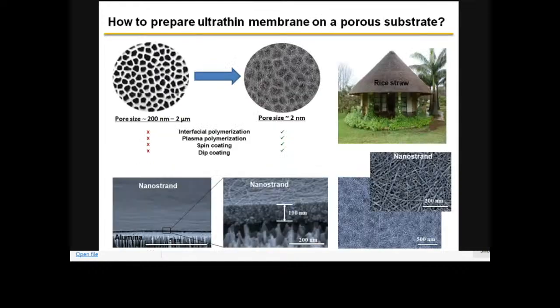Now, on a very big porous structure, how will you make a very thin film? There are many conventional polymerization techniques like interfacial polymerization, plasma polymerization, spin coating, dip coating. All four will not help much because the material will go inside the pores. You need a top, very thin, smooth layer so that we can have a higher flux. If it gets inside the porous structure, it will eventually form a very thick film, and that thick film will give you lower flux. So our interest is to make a very thin film on top of the porous structure.